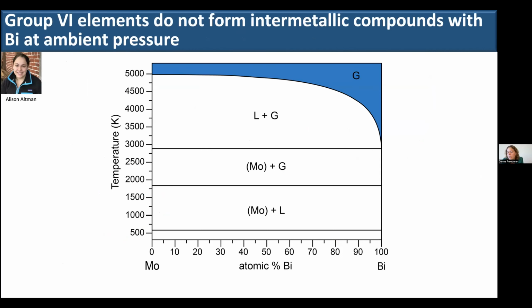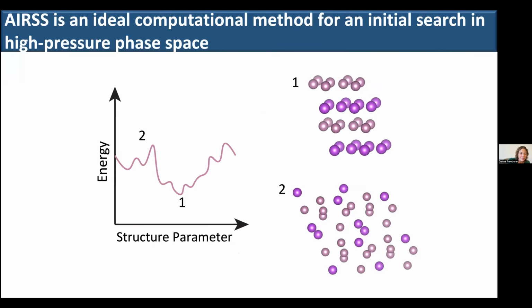Another system that we were interested in for all of the reasons previously described is looking at 4D elements. So expanding the catalog from 3D elements to 4D elements. And again, just like iron bismuth, for example, in the molybdenum bismuth system, we see effectively a large immiscibility gap. And this is work by Allison and again, James Walsh, who's at UMass Amherst, and Allison has just started her position at Texas A&M, where she's going to be doing some beautiful high pressure research of her own.